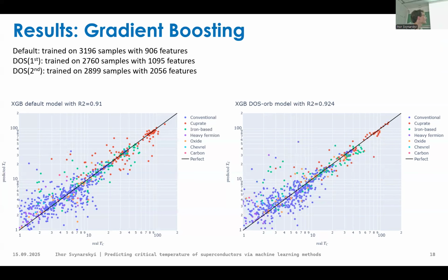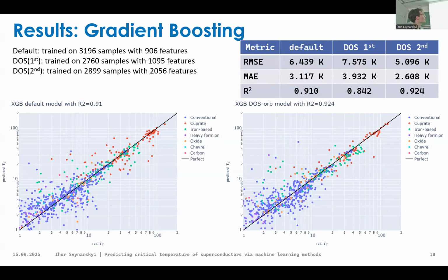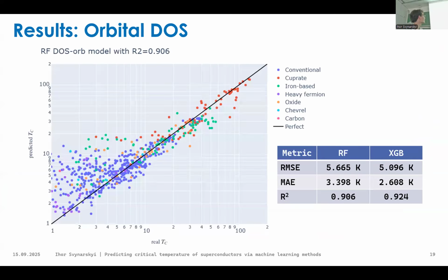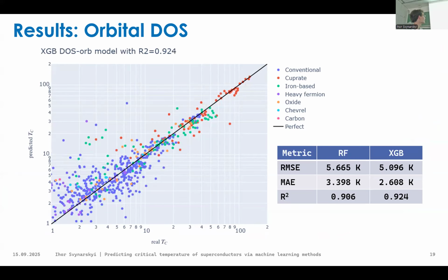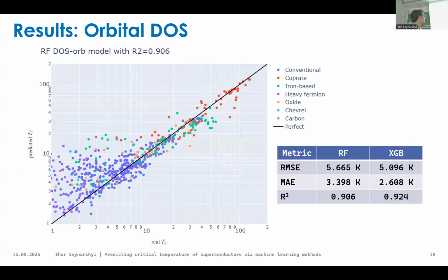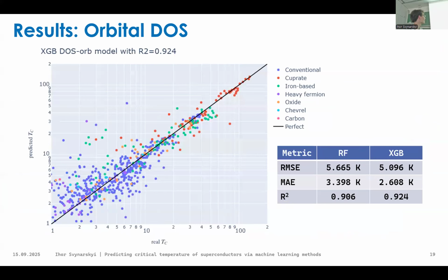And yes, using the DOS, we achieved more or less competitive results. And this plot is looking almost on the line. Comparing the two best results, random forest and gradient boosting, you could see that they're more or less lying on this line, and it's good in predicting cuprates, but for iron-based, it sometimes fails. And is this line for the training set or the test set? The whole set?